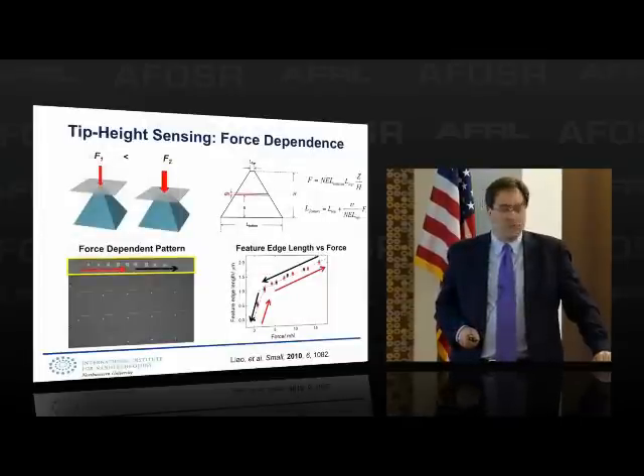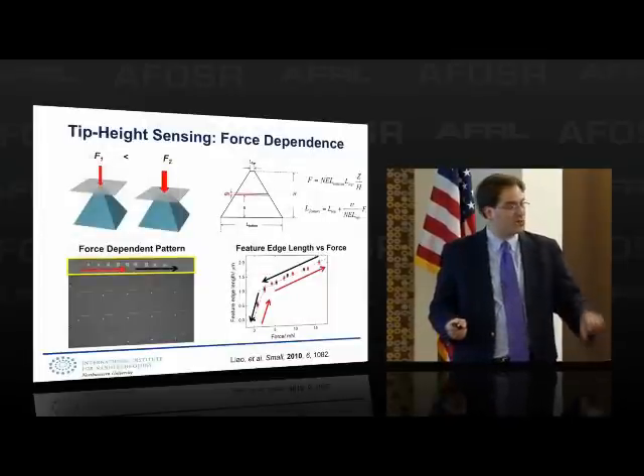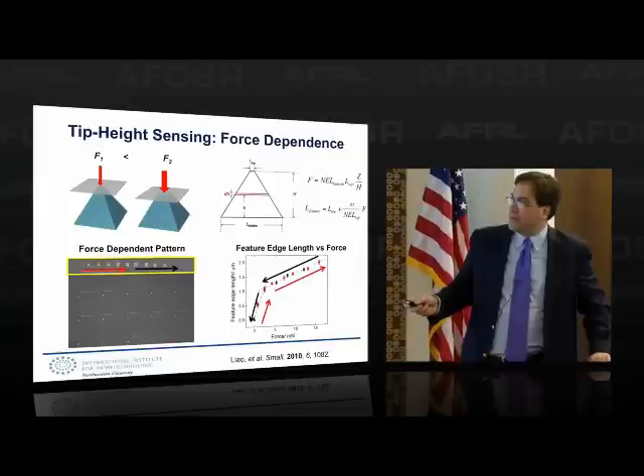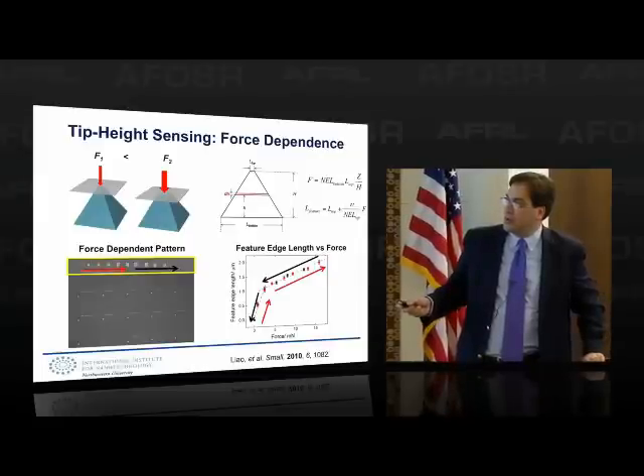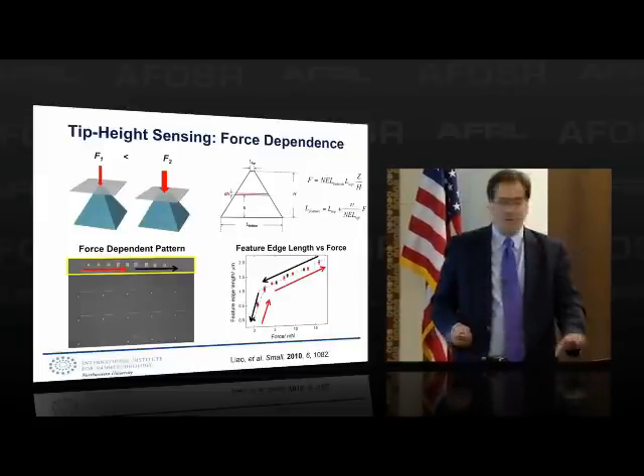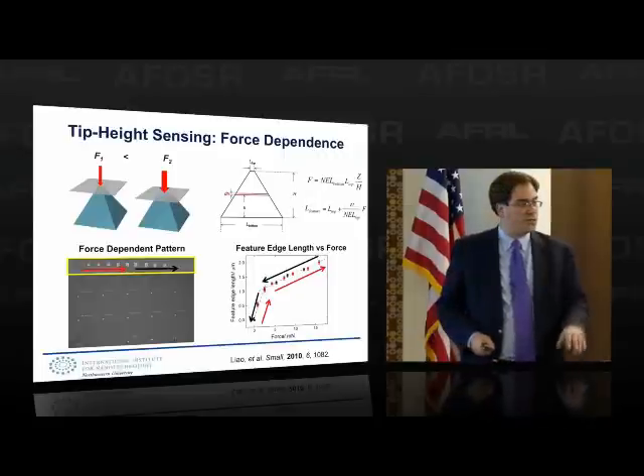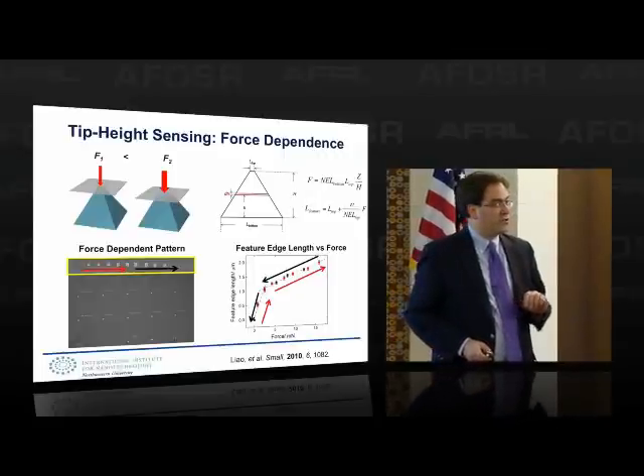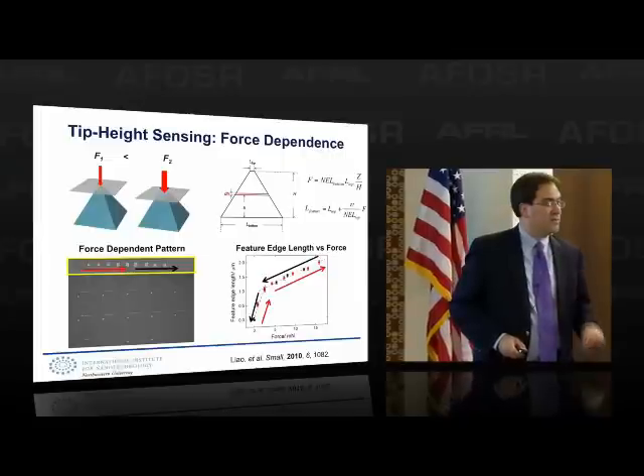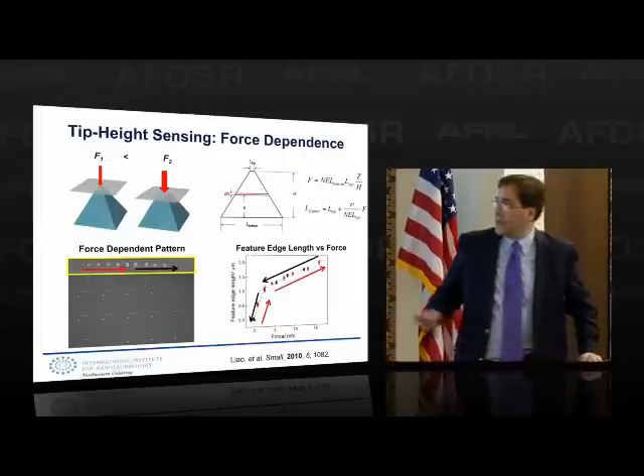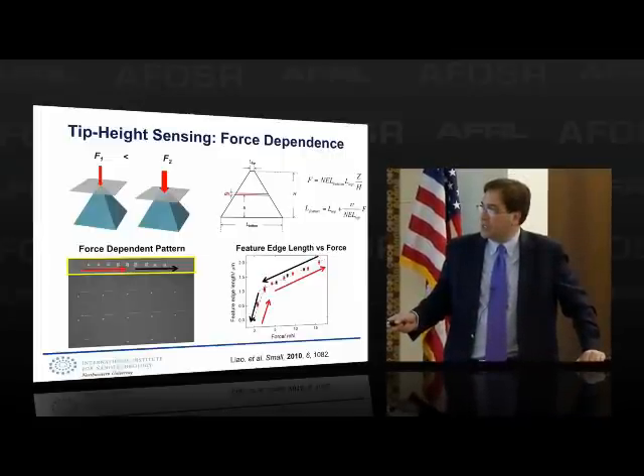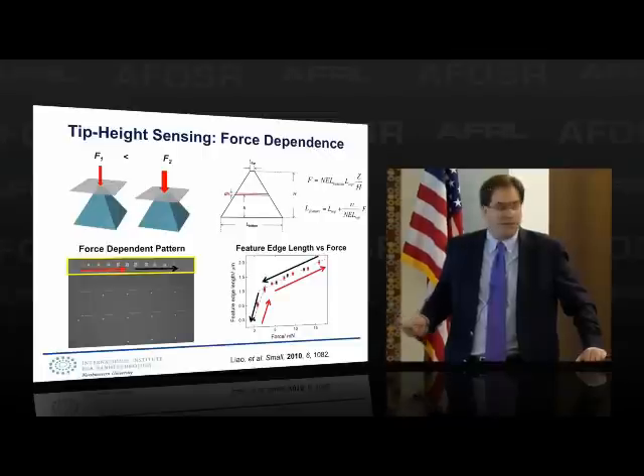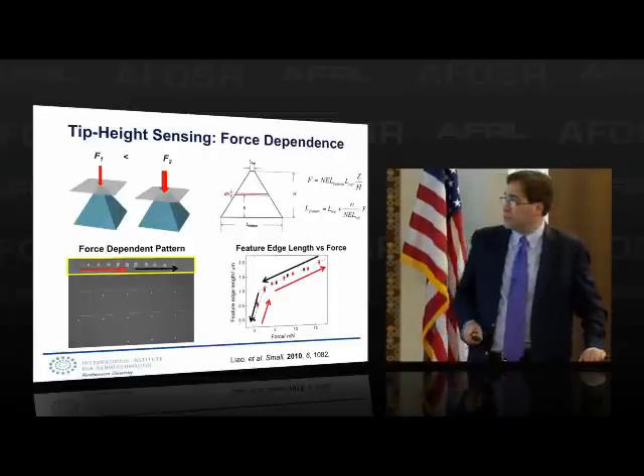This shows you the reversibility. This truly is a soft structure that's springy. If you think about it, as I push harder, I'm taking a deeper and deeper slice of the pyramid. That's why at large contact forces I could make those 600 nanometer features, and at very soft touches I could make those 90 nanometer features. This is pushing lightly, pushing hard, and then going back the other way. You can see it's remarkably reversible.